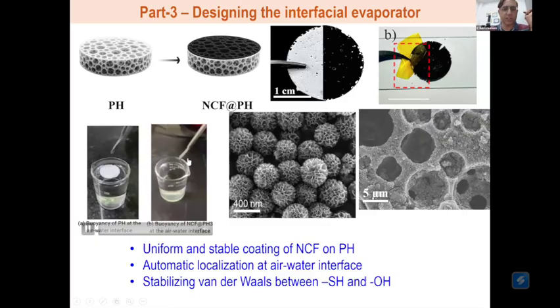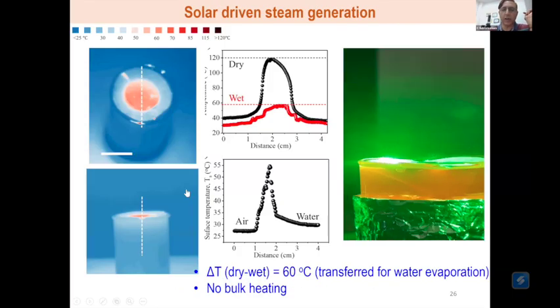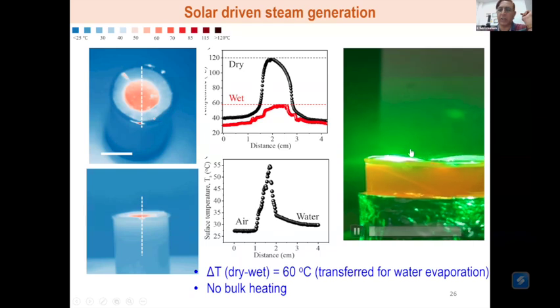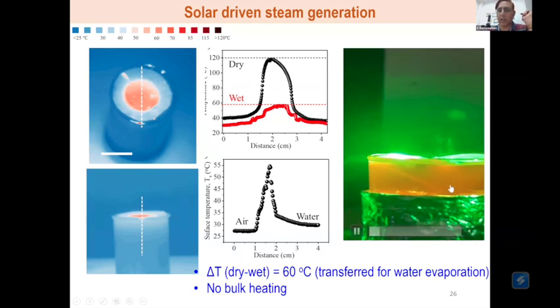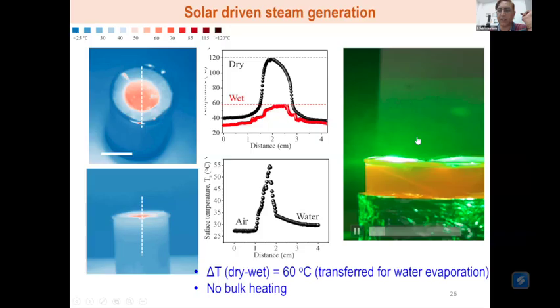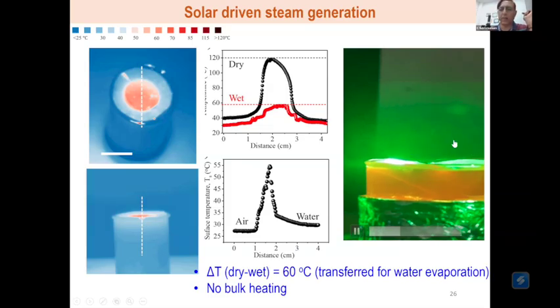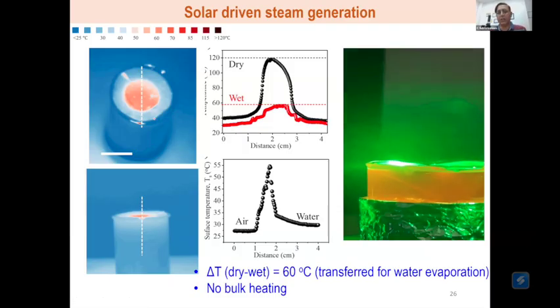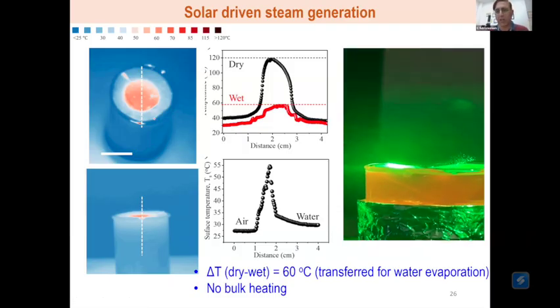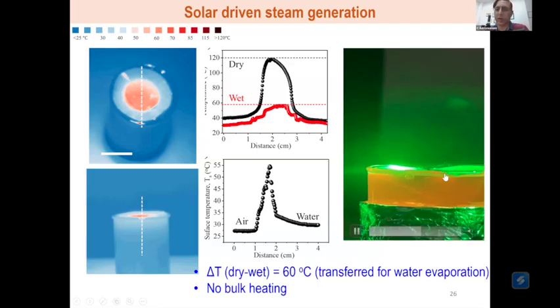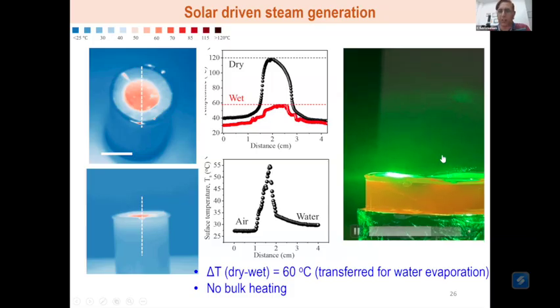And this was interesting because this gave us an opportunity for interfacial evaporation. So you take this material, it naturally suspends itself at the air-water interface. This is the interface where the sunlight reaches the coating. Water reaches it from the bottom, and you can see these droplets of water, which are now dyed, evaporating from the surface, because it is now able to pick up the heat from the NCF coating and evaporate and form water vapor. Of course, in order to see it better for a visual effect, we have added some dye molecules. That's why you see these water droplets or water vapor droplets as green in color. We have just added some rhodamine dye to it.